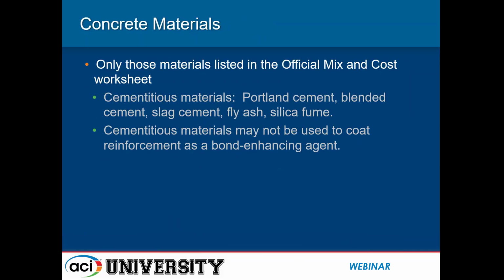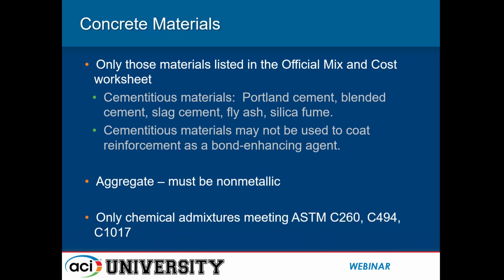For the concrete materials, you are only allowed to use materials listed in the official mix and cost worksheet. And we'll take a look at these specifically when we take a look at the worksheet. The cementitious materials include Portland cement, blended cement, slag cement, fly ash, and silica fume. The cementitious materials may not be used to coat reinforcement as a bond-enhancing agent. This has become apparent at previous competitions, and teams have been disqualified when we have identified the cementitious material bond enhancement. This is observed when we break open the member or it fails, exposing the bars. The aggregates must be non-metallic. And the only chemical admixtures that may be used are those consistent with ASTM C260, C494, and C1017.